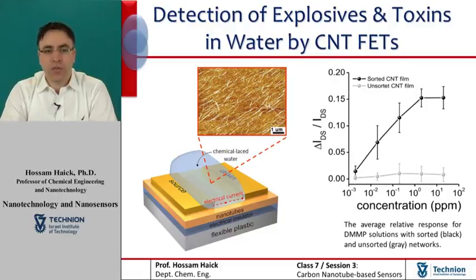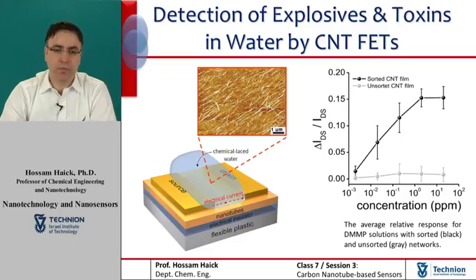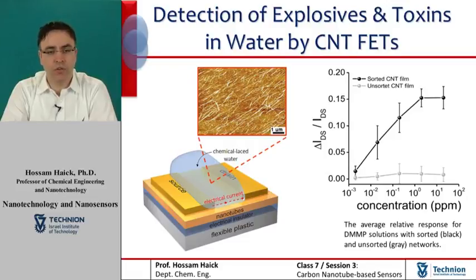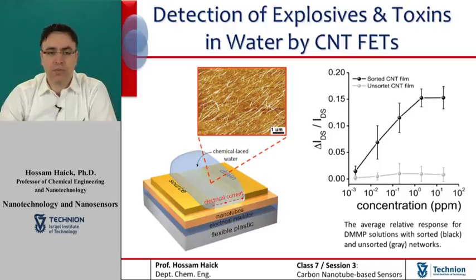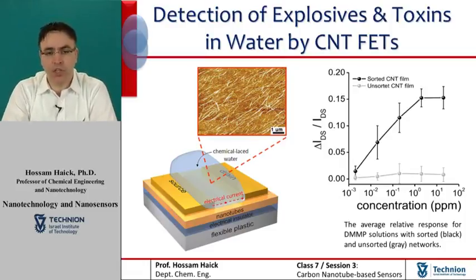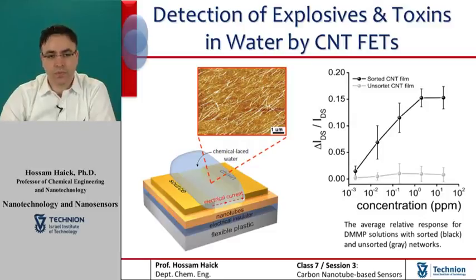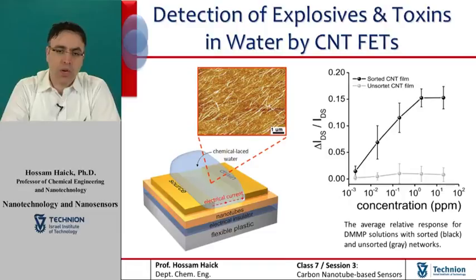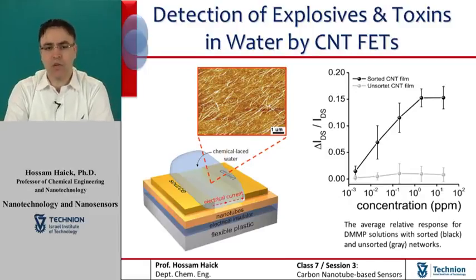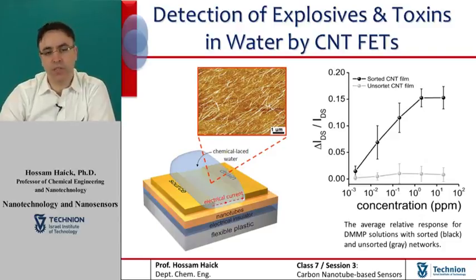The network topology of the sensor is extremely important for the analyte response of the single-walled carbon nanotube-based thin-film transistor device. A network of unbundled, primarily semiconducting nanotubes close to the percolation threshold provided good sensitivity and reversibility. Thin-film transistors of carbon nanotubes fabricated with either primarily semiconducting or metallic single-walled carbon nanotubes also show responses to TNT and DMMP solutions. The ability to assemble reproducible single-walled carbon nanotube films while simultaneously controlling the deposited tube type provides a unique opportunity to investigate the fundamental properties of the sensors.